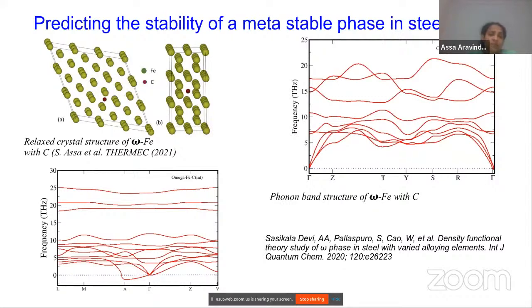So we tried to reproduce that, and what we have seen here is, I have just shown two representative phonon band structures. When carbon is in the substitutional position in this structure, we can see that the phonon band structure is giving only positive frequencies. So if we have only positive frequencies, this structure is stable.